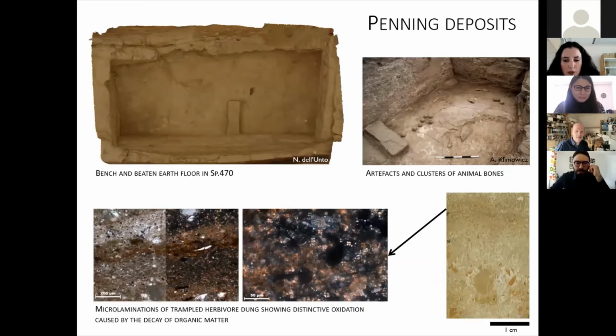Also at Çatalhöyük, micromorphology allowed the identification of several superimposed microlaminations of dung in space 470 that went completely unnoticed in excavation and that modified the original interpretation of this built environment. These dung remains were rich in partially digested plant matter found in association with thin and highly compacted undulating layers, which suggests substantial animal trampling.